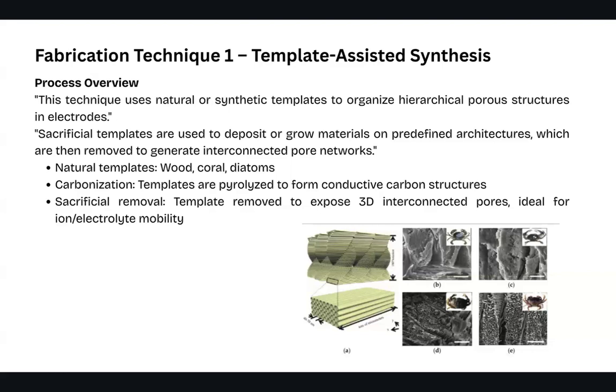pore networks. So we have natural templates, which are wood, coral, and diatoms, and this involves carbonization, where the templates are pyrolyzed to form conductive carbon structures. And we also have sacrificial removal. The template removal exposes the 3D interconnected pores, and this allows for electrolyte mobility.